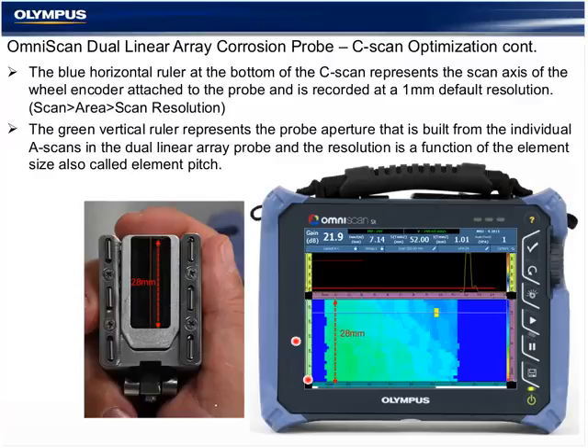This is in real millimeters. That's possible only at 0 degrees. And the blue ruler at the bottom of the C-scan represents the mechanical movement of either the probe on time-based inspection or with a wheel encoder, 1 millimeter at a time.